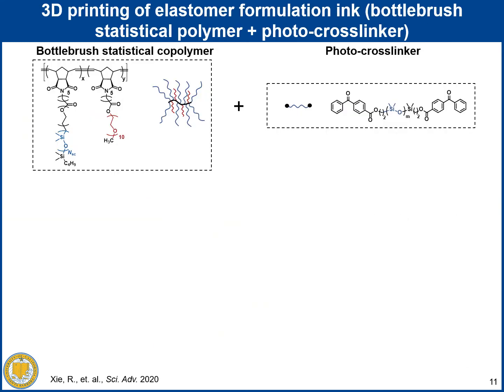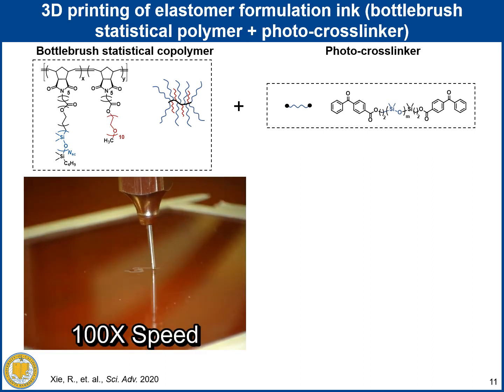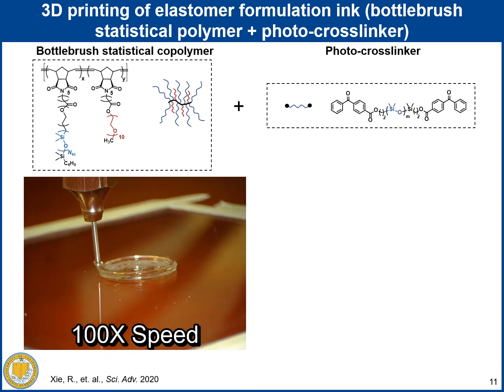But in order to transform the printed soft solid to elastomer, a small amount of photo-crosslinker must be added to the ink formulation without affecting the yield stress fluid behavior. Here, we demonstrate the excellent 3D printability of the elastomer formulation ink by printing a bowl-shaped structure.